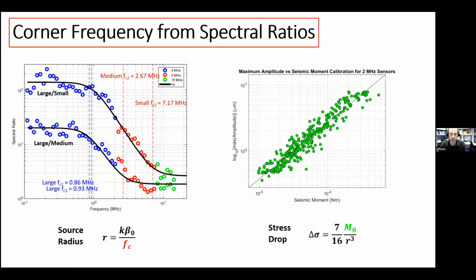And then it falls off until it turns over and we can get the corner frequency of the small event. Now, for a large versus medium event, this is the same large event. We measure roughly the same corner frequency, so that's good. And then the medium event, it should have a lower corner frequency than a really small one, and indeed it does. So it seems like this is working.